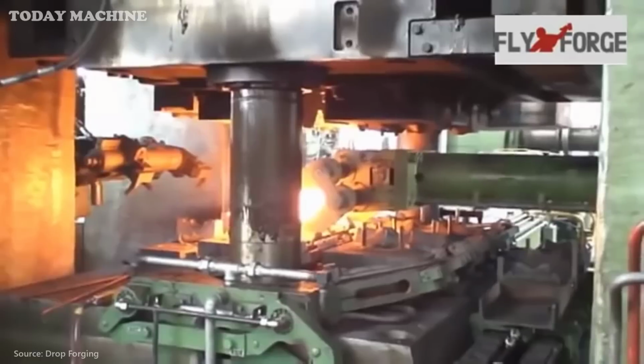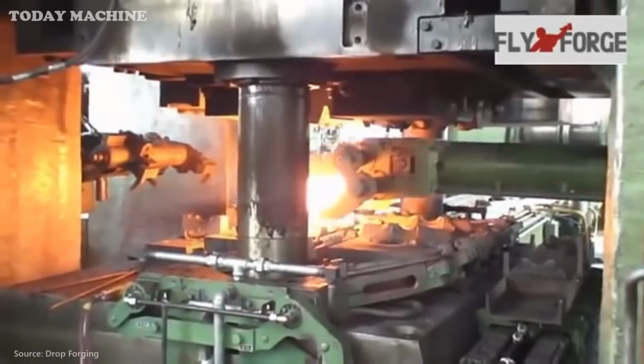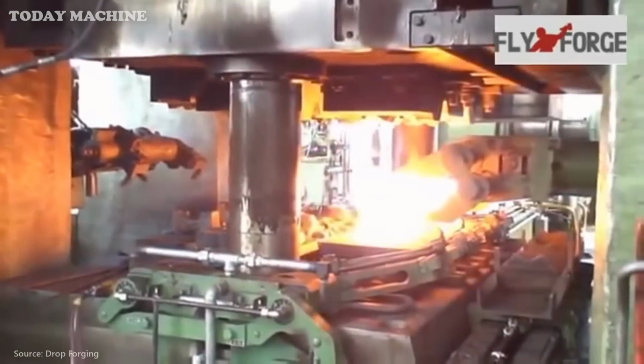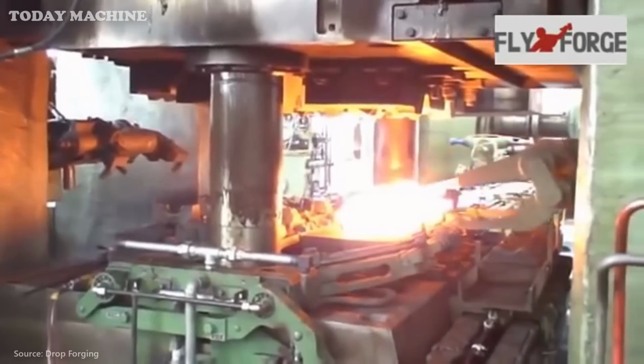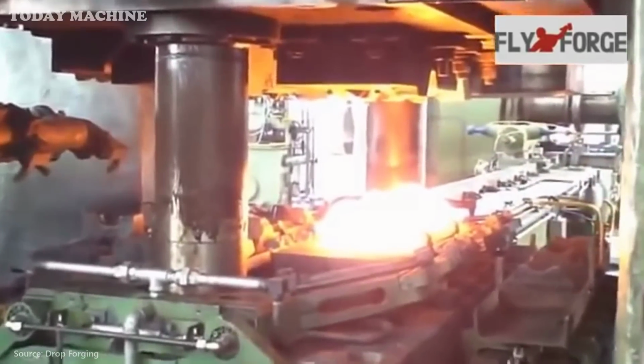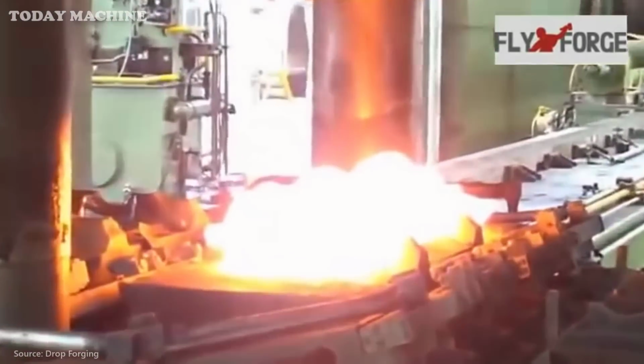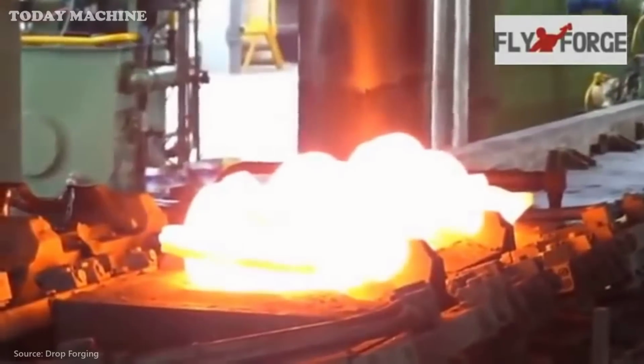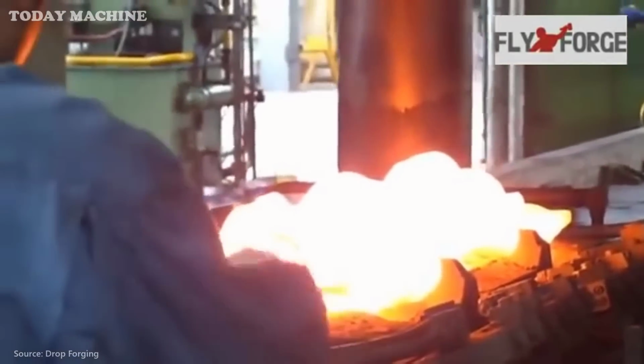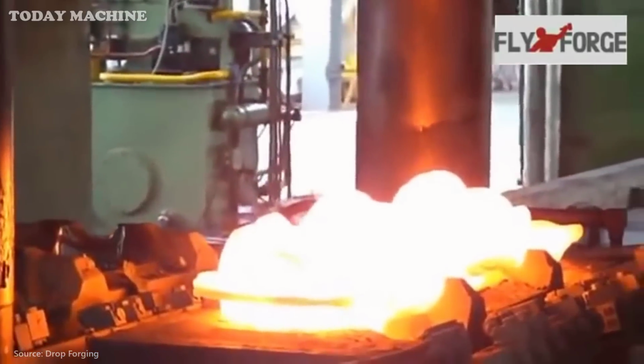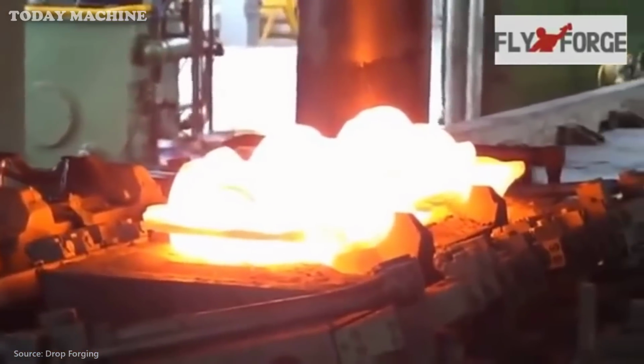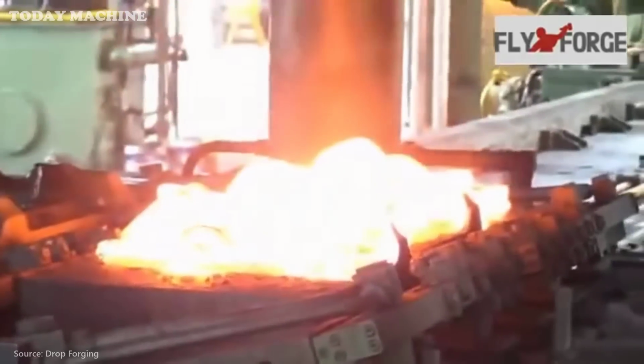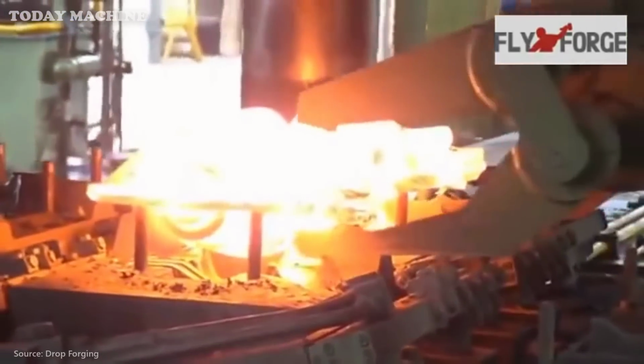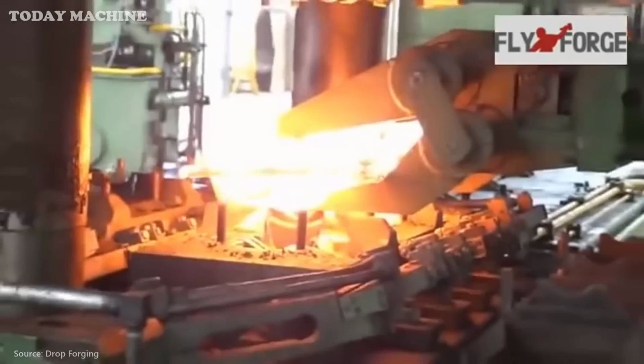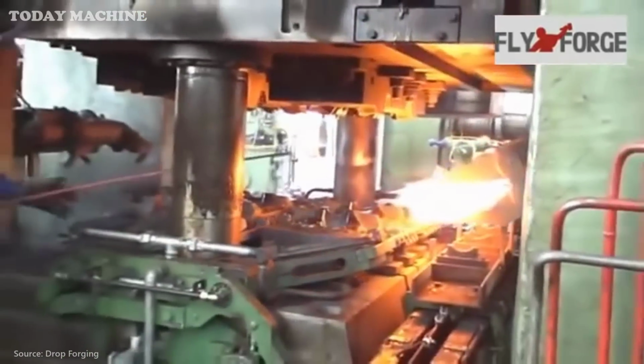The forging process includes pre-forging and finish forging. Pre-forging ensures even metal distribution, aiding the filling of the finish forging die and reducing die wear. Finish forging achieves the crankshaft's near final shape. After forging, excess material is trimmed off using a press. This step defines the rough dimensions and edges of the crankshaft.